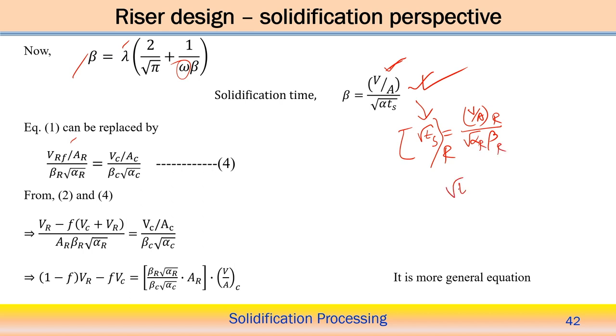And similarly, root TS in case of the casting should be V by A casting, square root of alpha C and beta C. If you put it, then this should be the same, equal to that. So riser and casting volume solidification time is the same. With this analogy we can modify this equation. So V by A riser, so V RF by AR divided by square root of alpha into beta R, then VC by AC for the casting, beta C by alpha C, so that should be equal.